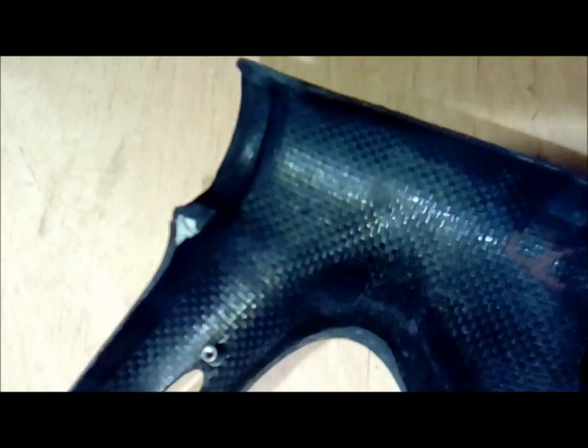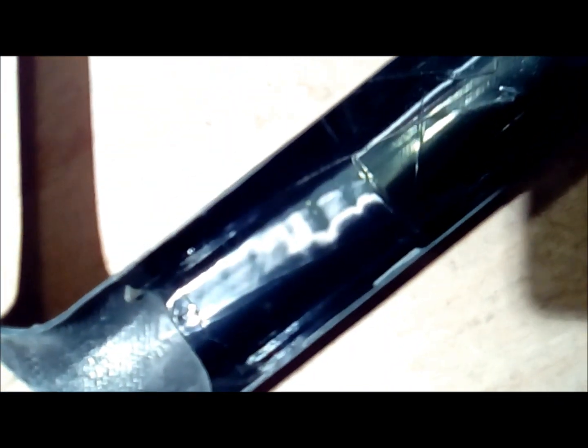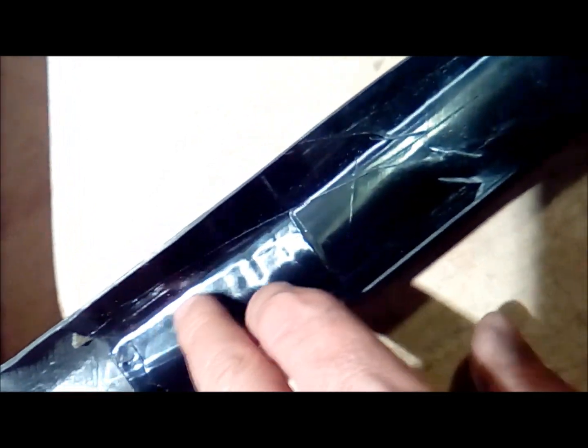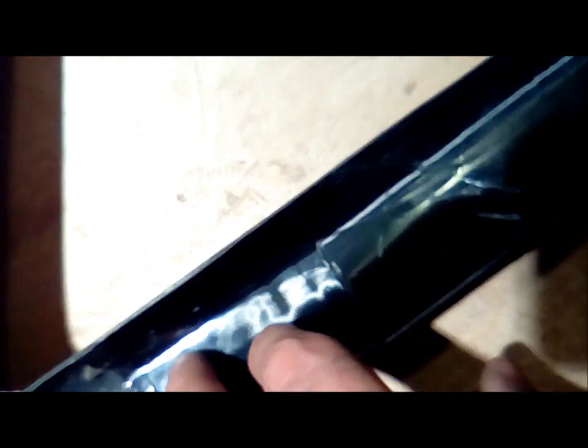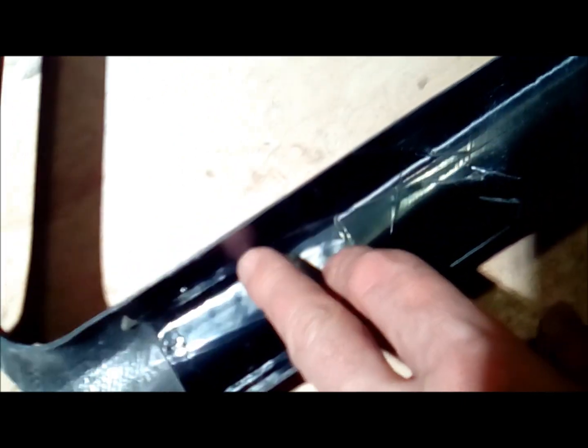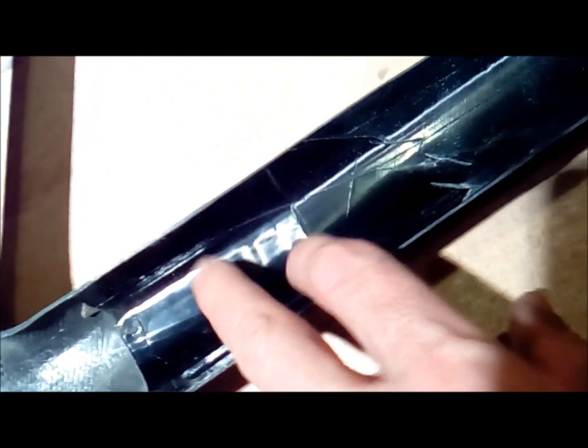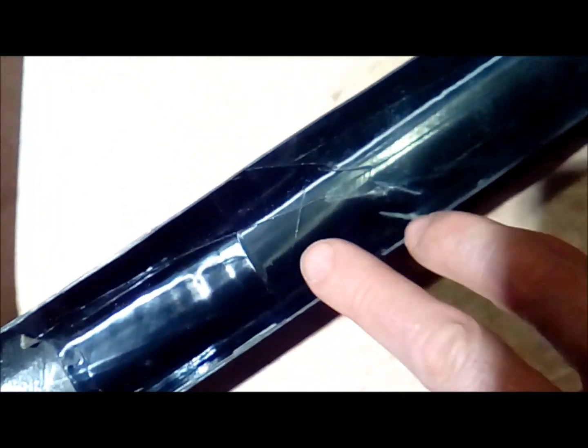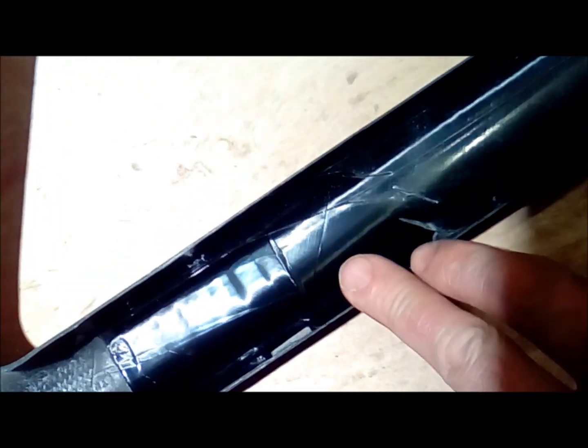I'm not a material science guy, but when it comes to carbon I like to see on the edges or throughout the laminate here, I don't want to see any voids. I don't want to see any evidence of delamination. When I'm looking at the carbon inside the tube, I don't like to see waves which would be indicative of maybe resin-rich areas inside, or in the carbon laminate itself. In other words, maybe not enough compression when the carbon resin laminate was curing. Obviously I don't want to see cracks.